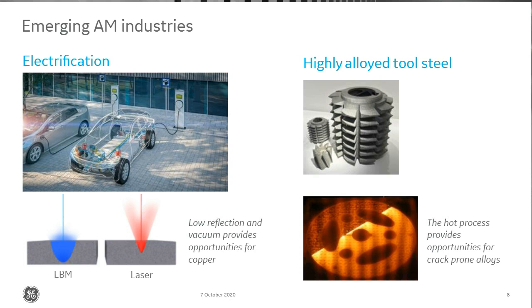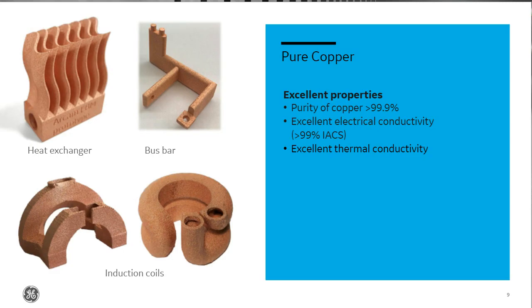If we start with copper, so Anders, what application examples has GE Additive so far explored? Yeah, we have a couple of them here on the screen right now. So there is a heat exchanger, perfect for cooling various electronic components. We have the possibility with the preform that additive brings, that Isaac mentioned. That goes actually for all of these parts. We have two induction coils that with additive you can print as one part. Normally you have to bend or weld these, but since they're printed, there is no stress in the material and, of course, no welding then.